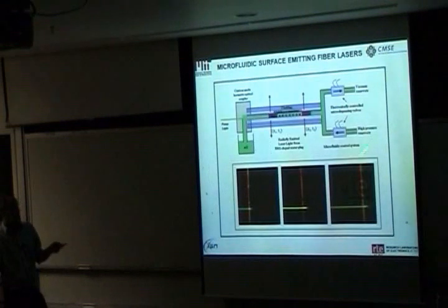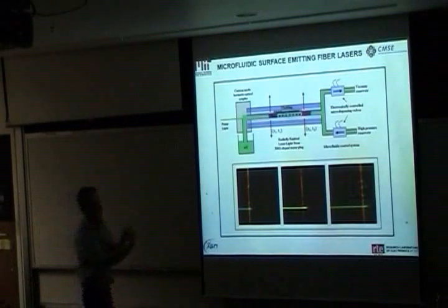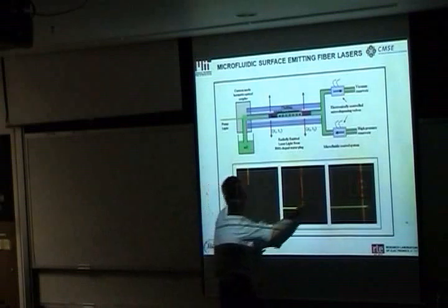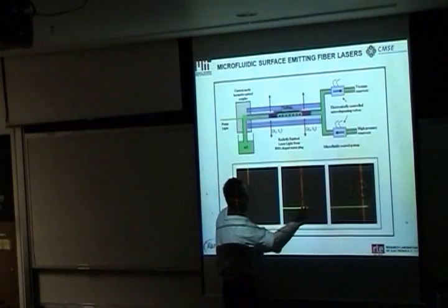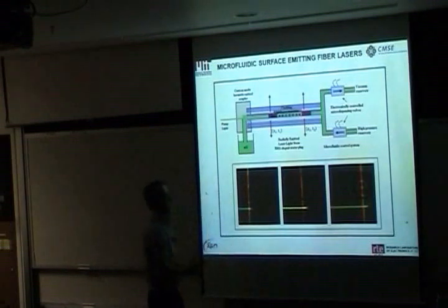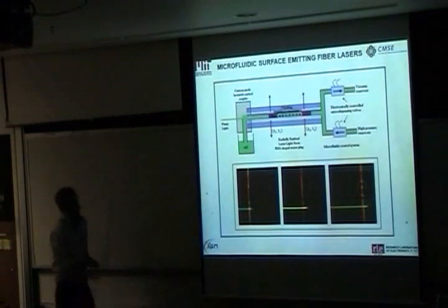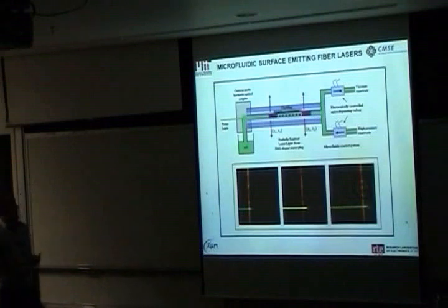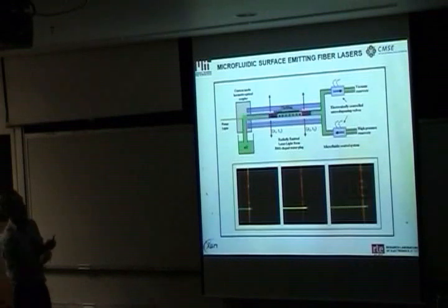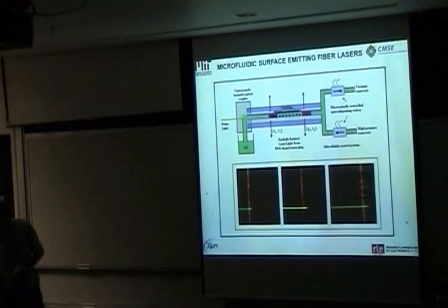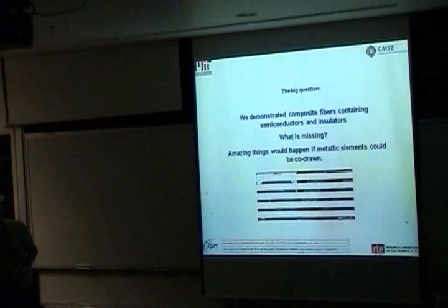And then the next step is to actually not fill it with a solid core, but use a liquid core. And by doing so, you could actually get control over where your fiber is lasing. And so here's the lasing plug, and this is the pump beam, and you actually get a very nice collimated lasing line. And that sort of borders or is a connection between microfluidics and the fluids that are flowing through this very small core, and the fact that you have this optical confinement mechanism.